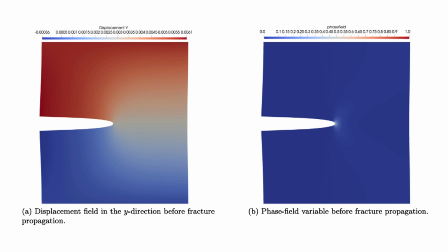It's quite elegant, actually. They perform an additive decomposition of the strain energy density, fancy term, but it just means they split the energy into two parts: one caused by tension or stretching, and one caused by compression or squishing. Okay. Split at the energy calculation.